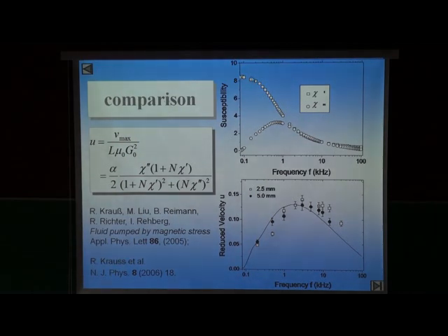These are the susceptibility curves. This is the imaginary part, and the square is the real part of the susceptibility. You might be familiar with this from the dielectric constant. It has a real part and an imaginary part, and the same is true for the susceptibility. It also has a complex susceptibility, and for very low frequencies you see that the imaginary part is 0.